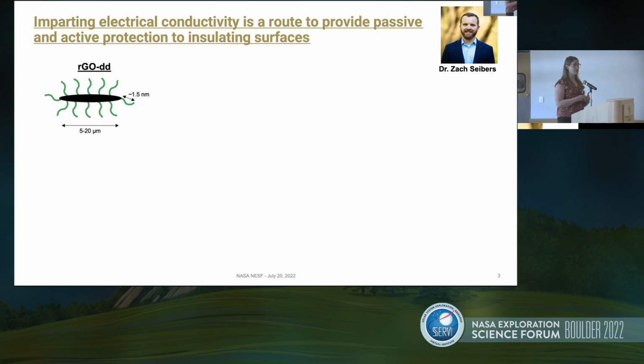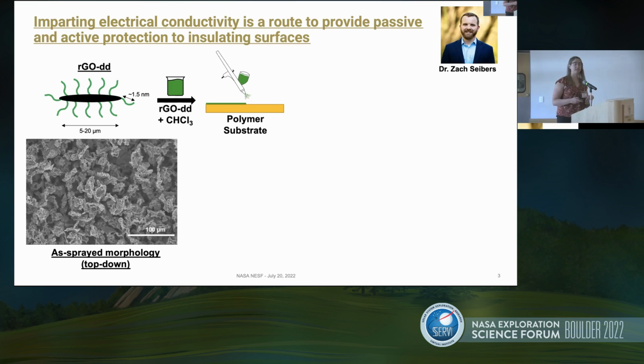So our approach to doing this is using a reduced graphene oxide chemically modified particle. So the concept here is that we have a conductive nanoparticle that we have grafted short polymeric chains to enhance dispersibility and miscibility with polymer matrices, which allows us to perform this processing. We take these particles, suspend them in an organic solvent. We typically use chloroform, although they're dispersible in a number of solvents. We use a commercial airbrush to spray them onto the surface.